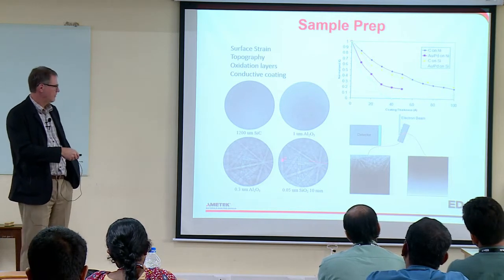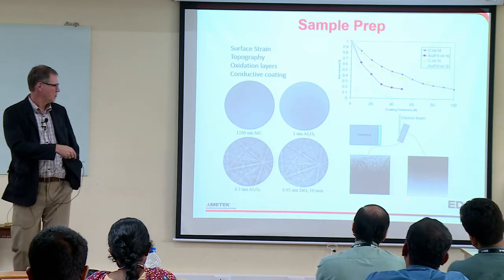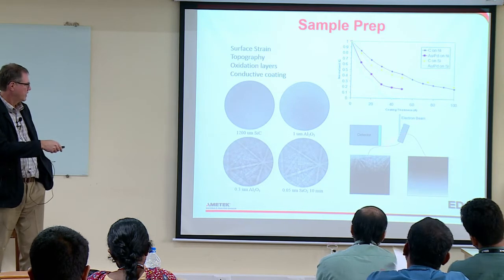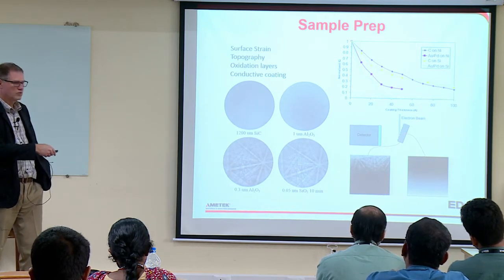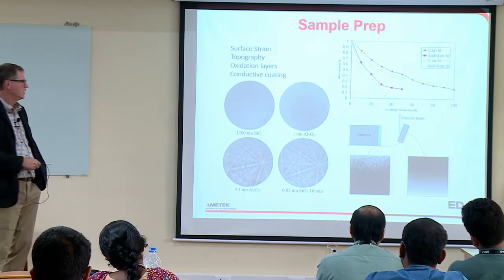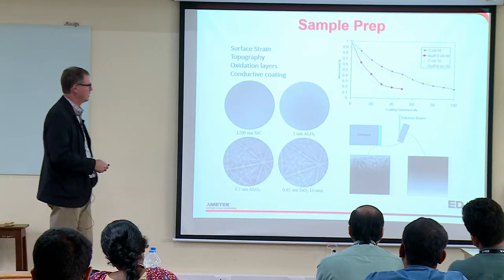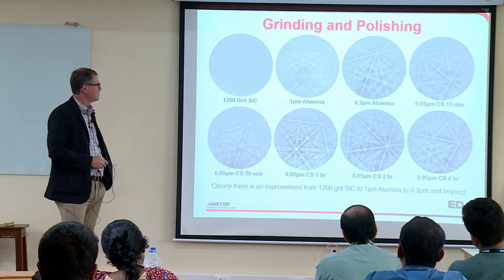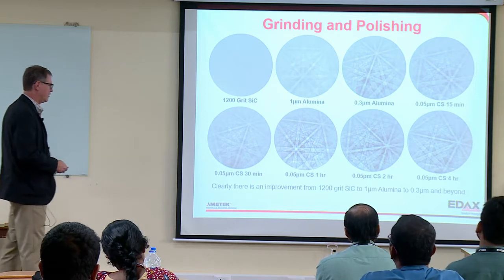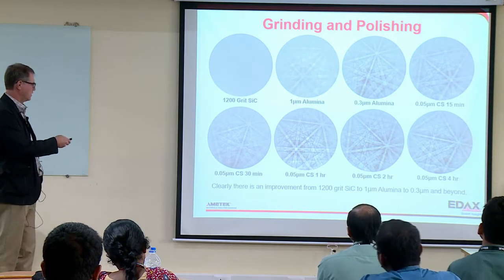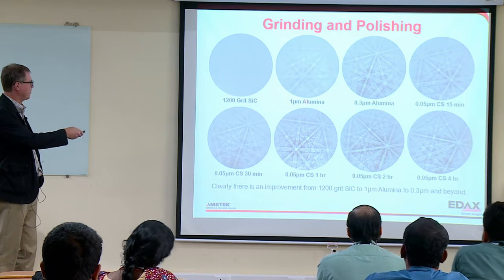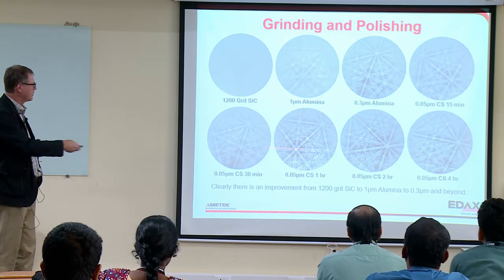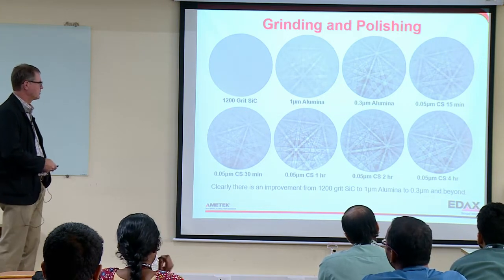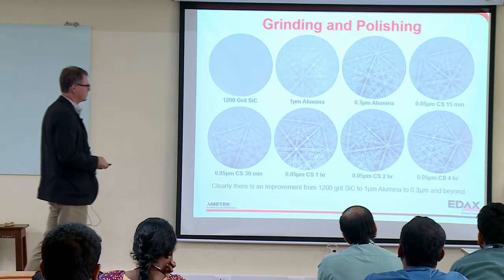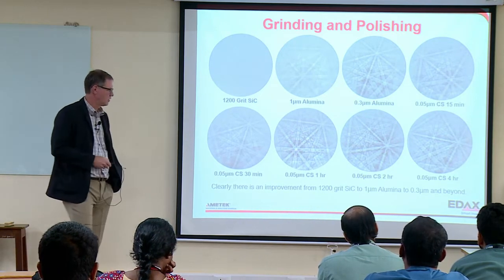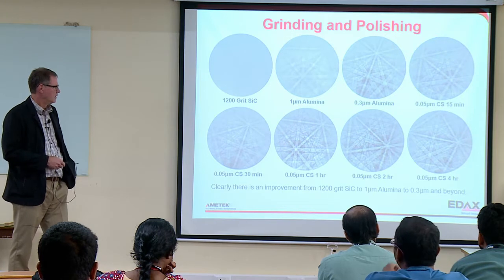Now, ideally you have samples that are polished, but just to show you, you can do rough samples. It's just that you get a gradient, which can make it difficult for the indexing routines to work, and I'll show why later. So this is just another sequence here. There's a lot of improvement when I go from the silicon carbide paper to alumina. Less improvement as I go along, but this is a really good example of nickel, so you really don't have to polish it as well as maybe some other things.